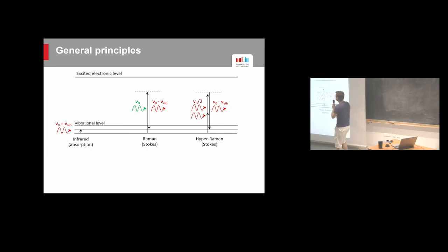Here is just the same. I just added another process here that I'm going to mention a little bit, just with one example, which is hyper-Raman. So what you're doing with hyper-Raman is that you're approaching your sample with a light of, say, half the energy. Two photons get absorbed, and you're checking the energy difference with respect to this second harmonic. Okay, it's a bit more rare, definitely not common, but useful for us because it gives us access to modes that would be otherwise not easy to measure.